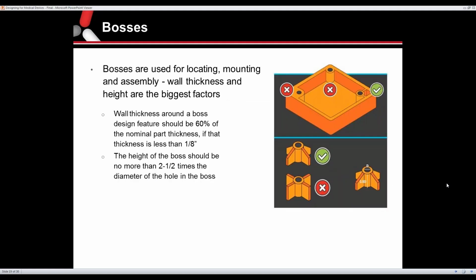So bosses are kind of tied to ribs. They're usually utilized for locating or mounting for some sort of assembly. Just like the ribs, the thickness and the height are the biggest factors. So the wall of the boss should be no more than 60% of the nominal part thickness, if that thickness is less than 1/8 of an inch, which is going to be most plastic parts. And then the height of the boss should be no more than 2.5 times the diameter of the hole that's within the boss. So we've got some examples there on how to tie ribs into corners of a part.